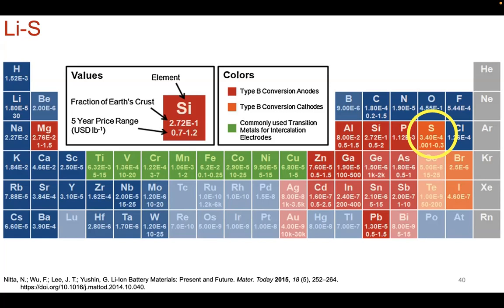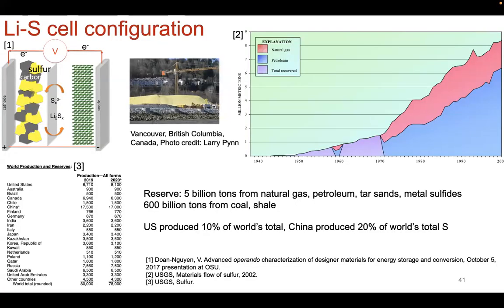Now, we talk about sulfur and its advantages because it's readily available and quite cheap, and that we can see. In terms of fractions of the Earth's crust, it's relatively high compared to the 3D transition metals here. In terms of cost, you can see here, US dollars per pound, it's like $0.001 per pound relative to, let's say, $10 per pound for cobalt. And that's just the minimum values in the range. So that's pretty attractive. And one of the reasons why the sulfur cost is so low is because it's a derivative